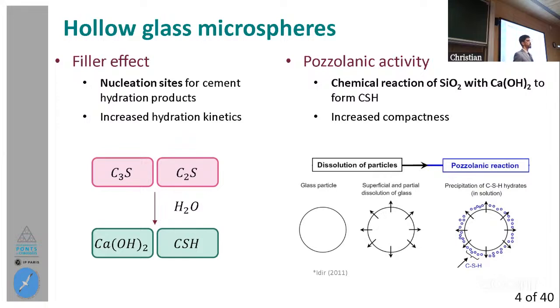For understanding this, we have to understand basically what cement hydration is about. So what we have is that the clinker is composed of tricalcium silicate and dicalcium silicate that will react with water during cement hydration to form calcium hydroxide and calcium silicate hydrate. So knowing that, we know that these spheres may present some filler effect, which in the context of this thesis, not in the scale of the sphere but in the scale of the hydration products, may act as nucleation sites for cement hydration products, which will increase the kinetics of hydration and also improve the compactness of the material.